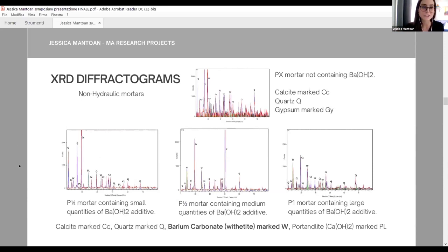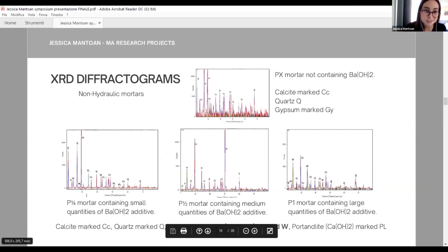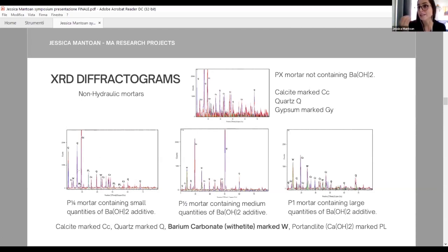Even more interesting for non-hydraulic mortar is that, considering that XRD is not just a qualitative analysis but also a quantitative one, the intensity of the peak gives us information about the amount of the compound in our sample. In this case, for the mortar containing a small quantity of barium hydroxide, the witherite peak, so the barium carbonate peak, is really small because we used a little additive. For mortar containing a medium quantity of barium hydroxide, the peaks increased their intensity, so the amount of material is bigger. And in particular, the witherite peak is exactly half of the calcium carbonate peak, as we said in the preparation of the sample.